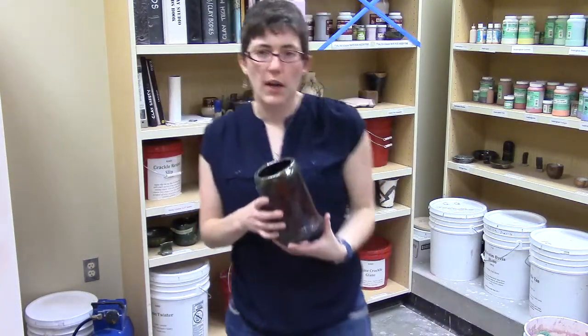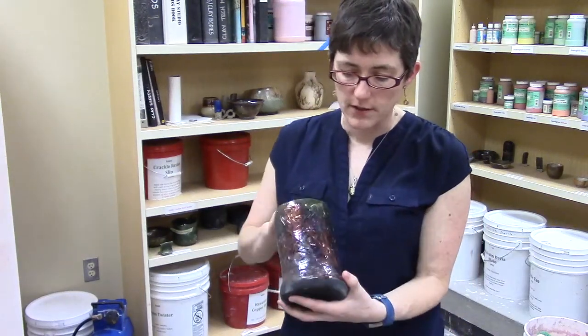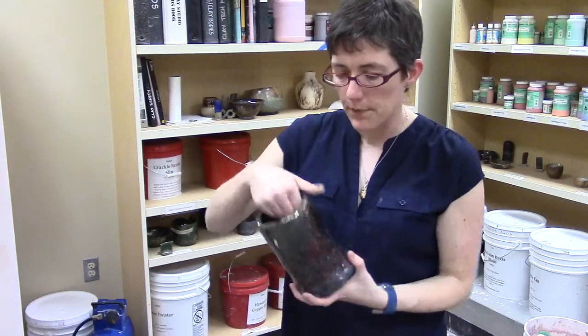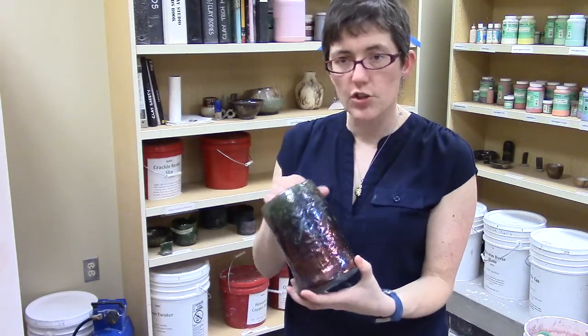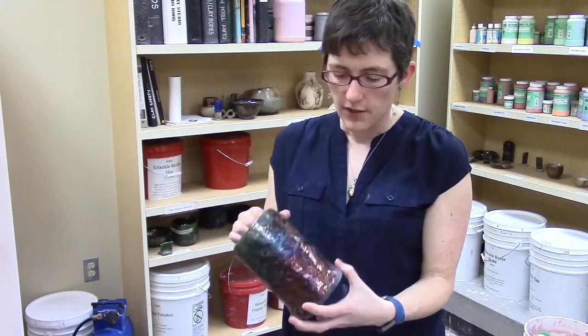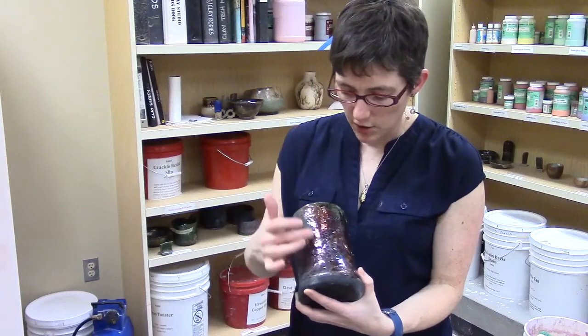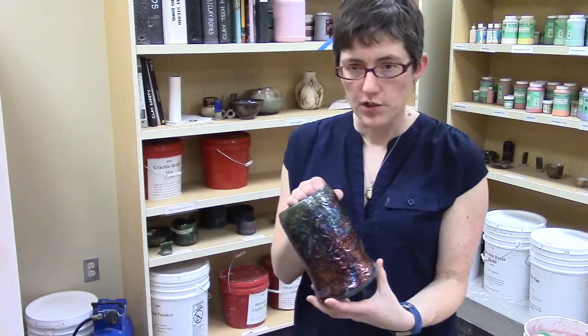The other kind of glazes that we have for Raku are the luster glazes, the copper glazes. This glaze has copper in it, and you don't see a lot of cracking, but you do see the black area where the smoke is absorbed into the exposed clay. The copper itself has changed color because of that violent reducing atmosphere — the post-firing reduction that has a lot of smoke, a lot of fuel but not much air. It causes the copper to turn green where it has some air, to turn reddish coppery, and sometimes even to turn blue or purple.